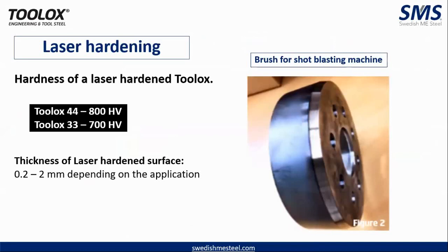So adding to the induction hardening, we have one more surface treatment facility, which is laser hardening. This can also be laser hardened. Here you can achieve up to 800 HV in Toolox 44 and around 700 HV for Toolox 33. The thickness of the laser hardened surface goes up to 0.2 to 2 mm, depending upon the application you can